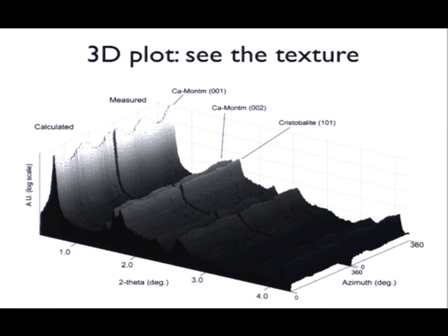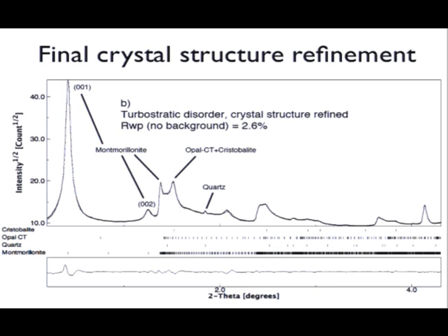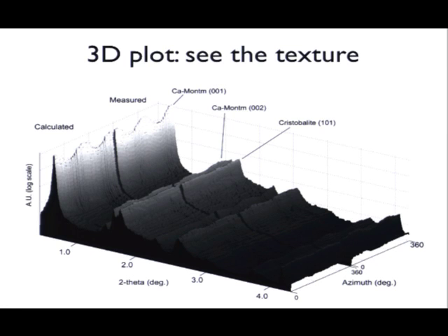So did the texture turn out okay? Well, actually what you see here is just, normally we work with 72 patterns. We actually divided our image in 72 patterns. We fit all the 72 patterns together with the texture. What you see here is just the final summation in the plot, okay, of all patterns, both the data and the fitting, okay? So when you want to see also what is changing with the pattern number, or here you just look at the azimuth angle, then you see, well, mainly on the 00L peak, the calculated and measured intensity, but also over here.